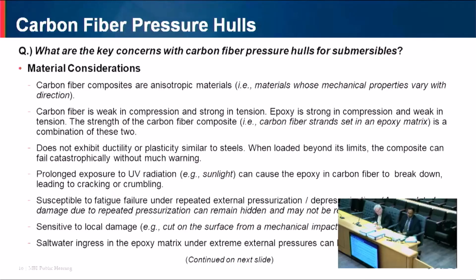So if you take a spherical pressure hull versus a cylindrical pressure hull of the same thickness, when exposed to the same pressure, you will see that the hoop stress in a spherical pressure hull is half that of a cylindrical pressure hull. Okay? So if you see a cylindrical pressure hull being used beyond 1,000 meters, it is pretty unusual. Okay? So now, what are some of the key concerns with the carbon fiber composite pressure hulls?